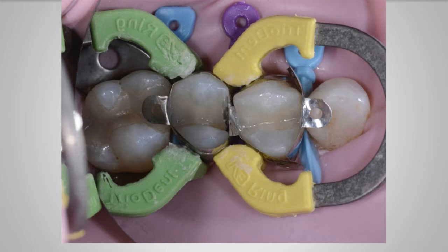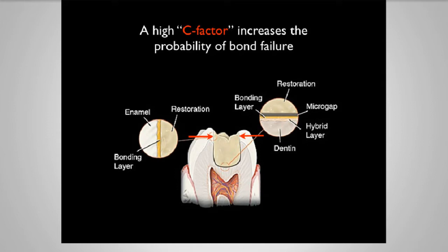I'm not going to do a corner by corner type situation because I want to be efficient, but also I'm concerned about issues with contraction. And one thing that can happen if you just bulk fill that whole restoration and then cure it hard, there's a situation that develops called C factor, and that's the stresses that are incurred by pulling those 2 cusps together when you cure that restoration. So one of 2 things is going to happen. You're either going to get stresses inside the tooth that are internal, or you're going to get marginal breakdown of the material at the bonding surface, and neither of these are good. So by filling one side at a time and curing it and then filling the other side at an angle, for me, that's my quick, efficient way to reduce C factor.